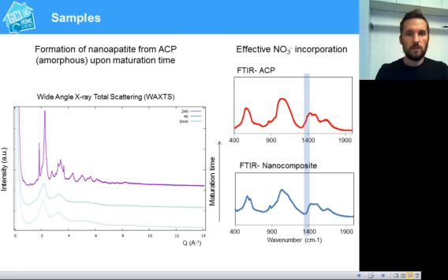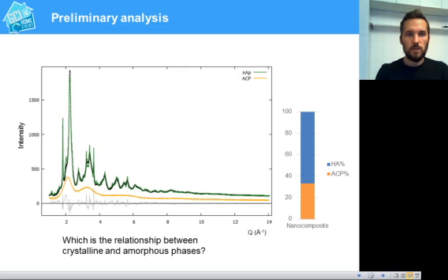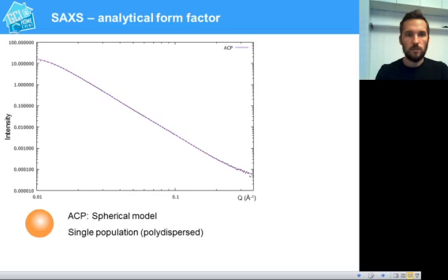Focusing on the nanocrystalline material, preliminary analysis showed that this sample is partially composed of an amorphous phase, accounting for nearly 30% of the sample. So we wanted to explore the relationship between amorphous and crystalline phase within the sample. To do this, we rely on the small angle X-ray scattering technique, which is blind at the atomic scale but sensitive to define size and shape of nanoparticles at the nanoscale.